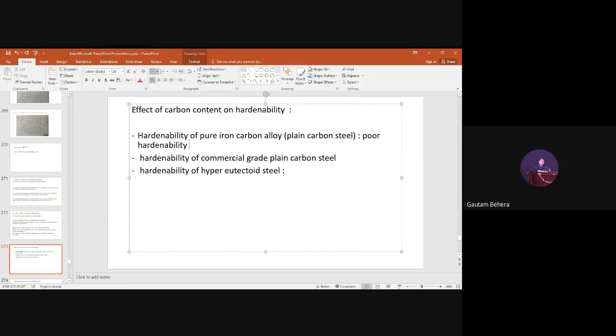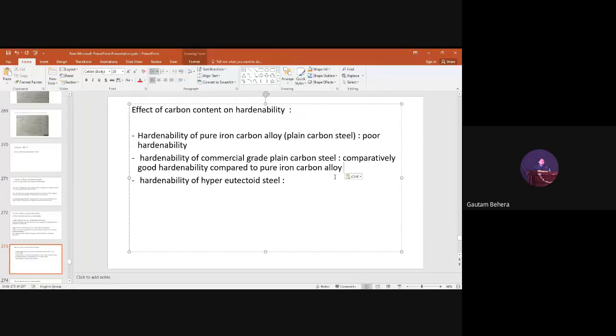And similarly, hardenability of commercial grade plain carbon steel. This is important because if you look carefully into the chemical composition of commercial grade plain carbon steel, it is only carbon that is there as an alloying element, right? But commercial grade means we anyhow have a certain amount of manganese, or some impurity elements, which will always be there in plain carbon steel. So it shows comparatively good hardenability compared to pure iron carbon alloy, right? Because pure iron carbon alloy means only carbon is there, but commercial grade plain carbon steel means some manganese content may be there.